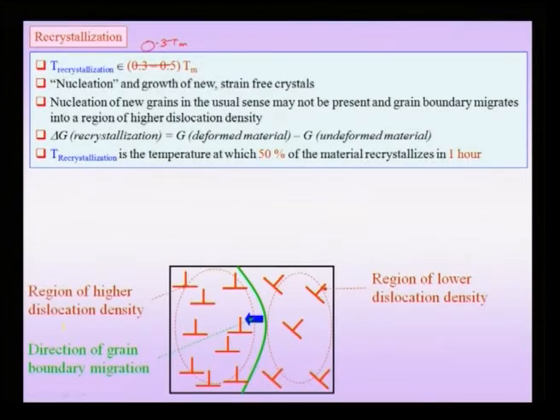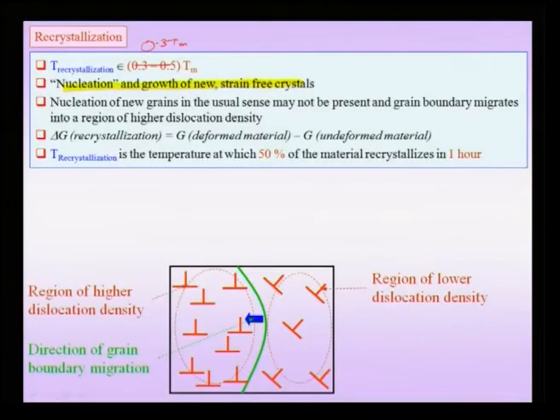That means now we can have nucleation and growth of new strain free crystals, and this implies that the dislocation density and the vacancy or the point defect density in these new strain free crystals will be very small, and the material would have been restored to its original annealed state which was present before cold working started. So we can have nucleation and growth of strain free crystals. Sometimes nucleation of new grains in the usual sense may not be present, and grain boundary migration to regions of higher dislocation density may lead to the formation of strain free grains.